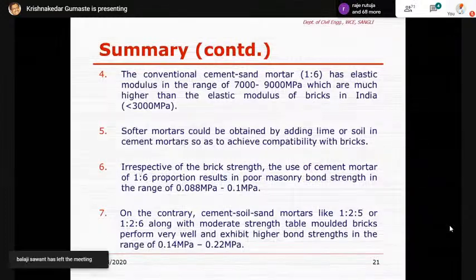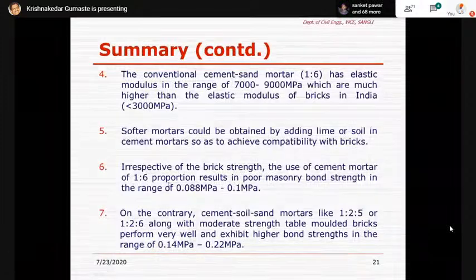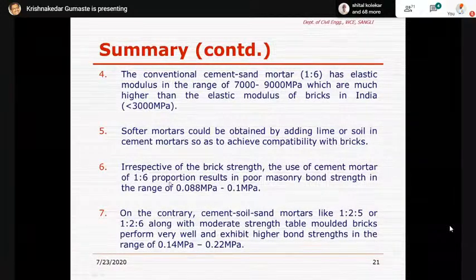The conventional cement mortar has an elastic modulus of the order of 7,000 to 9,000 megapascals, which is basically higher than the elastic modulus of bricks in India, which is limited to about 3,000 megapascals in general. Soft mortars could be obtained by adding lime or soil in cement mortars so as to achieve compatibility with the bricks. And irrespective of the brick strength, the use of cement mortar of 1:6, which is conventionally being used,